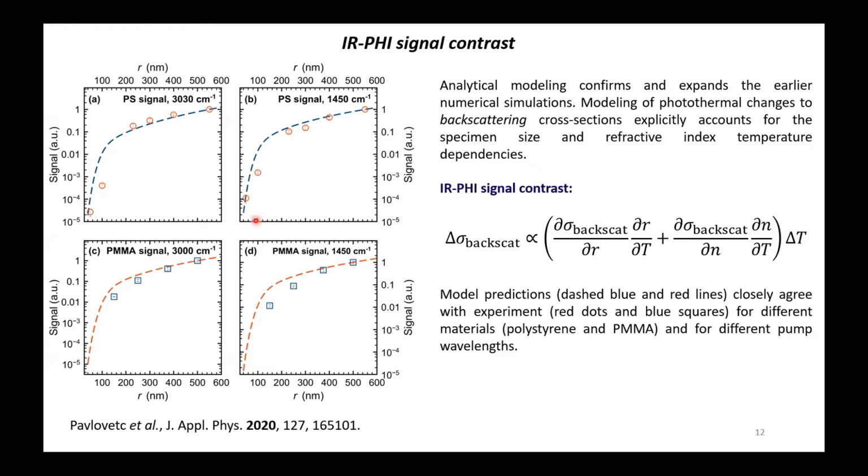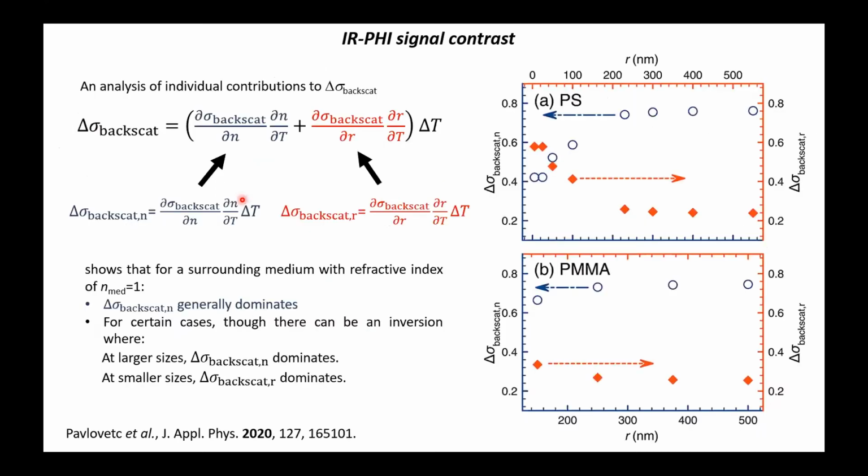And comparing it to real experiment, here for different samples with different sizes, we see that it agrees very well, and it captures a very steep signal drop for very small particles when it hits a Rayleigh scattering regime. So this is very exciting for us.